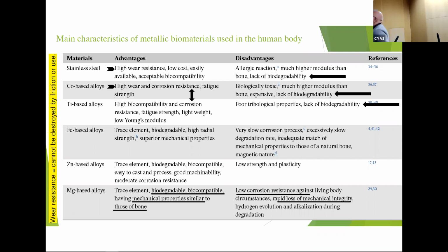So in comparison, magnesium is biodegradable, biocompatible, with mechanical properties similar to those of bone. So it's perfect. But the problem of magnesium is its low corrosion resistance. This low corrosion resistance leads to hydrogen bubbles, and after that some kind of dissolution makes a product, magnesium hydroxide, which increases the level of alkalization around the tissue, and that's not good.